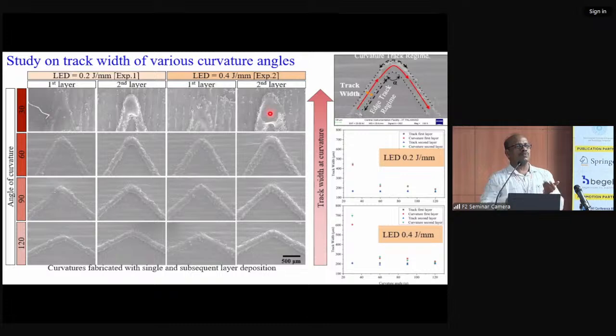The problem is that your powder is stationary and you are taking a laser and passing it. Whenever the laser takes a turn, it stops for a moment. That means it decelerates and again accelerates. You can't stop the laser, so more energy goes in and melts the material. That is the reason, especially in the bend, that you will have more material. So that should be optimized.